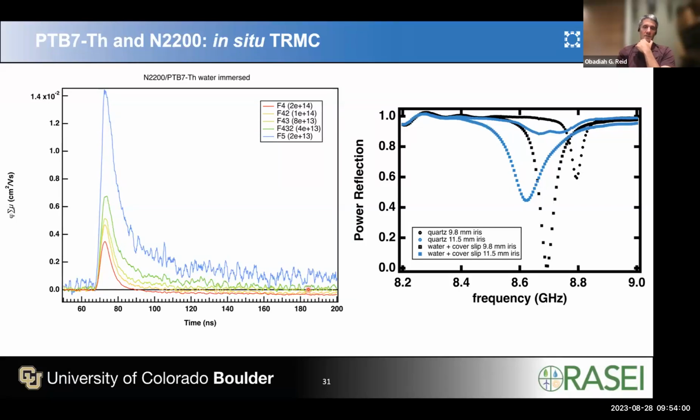And that is honestly the primary thing that makes this experiment difficult, this known artifact that we discovered when we were doing work in biolec over the prior 4 to 5 years. But here, the photoconductivity from your sample is quite a bit stronger than that artifact. And also the artifact is linear in power, whereas the signal is on this scale superlinear in power as you go down in laser power. So we can get around that, which I'm very pleased about.